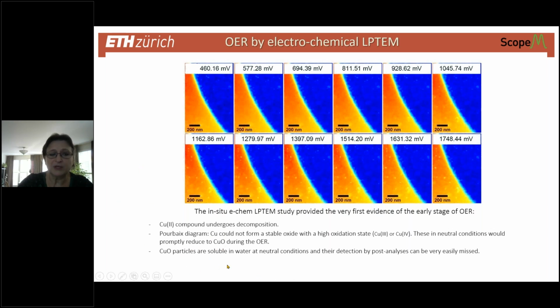Next, small copper oxide particles are pretty much soluble in water at neutral conditions. This is why they were not detected or reported in a publication consistently before. That's why they can be missed. So one has to look closer and then one sees them. The best would be, of course, to know the oxidation state of the species. One has to use some other reliable technique, because EELS through the whole sandwich of silicon nitride membranes with 500 nanometers, when they bulge even thicker, of basically water, is way too thick. We didn't see anything with EELS signal.